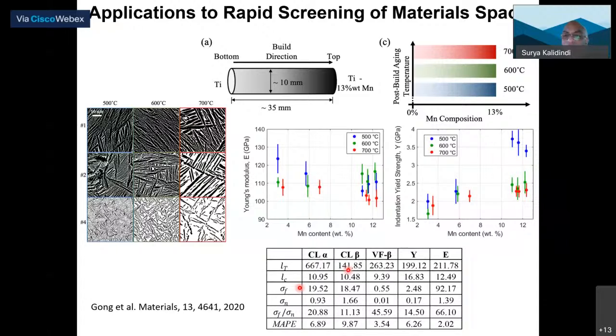But using these Gaussian process models that I talked about, you can also ask about sensitivity and things like that. Once you start analyzing this, you can tell which are the more important variables. For example, what this says is that the chord length in the beta, so the size of the beta, is a lot more affected by the temperature, because that has one of the lowest values here. The lower the value of L in the GP models, the higher the sensitivity. So you can understand what the sensitivities are, which then informs you as to what you should be doing next. If I'm not happy and I think I didn't cover my space well, depending on the target I have, what other experiments should I be doing? So that's what that helps.